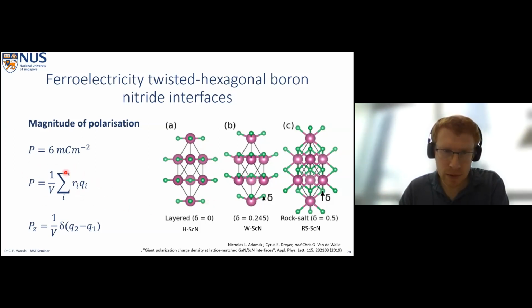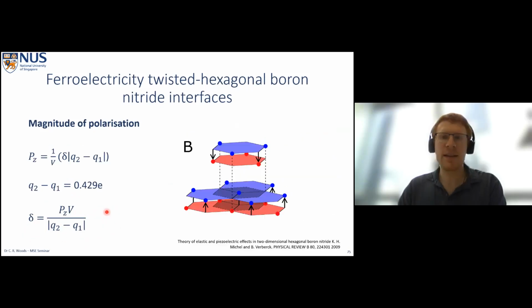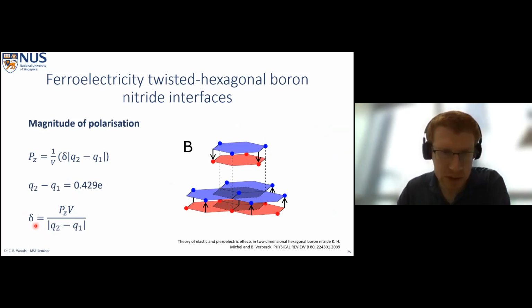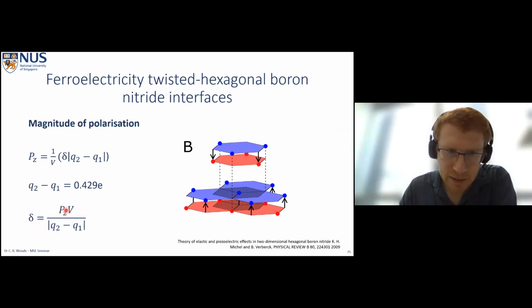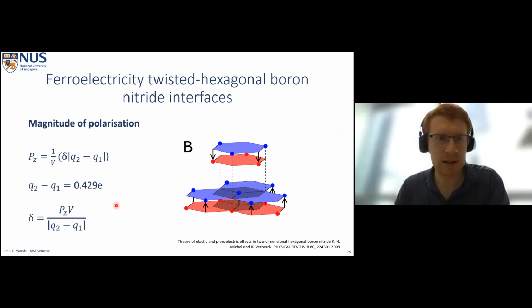And we can have quite a simple model for this, where the polarization is just equal to 1 over the unit cell volume times the sum of the weighted charge against the position within the unit cell. So we can simplify that further to this equation, and we can get that the distance delta that we would have to move up the nitrogen atoms or move down the boron atoms, whichever way you like to think about it, is just our polarization in the z direction times the volume of our unit cell over the magnitude of the charge difference between boron and nitrogen. So this is just the polar nature of our bond. If it's 0, of course, we'd have to displace them an infinitely large distance.